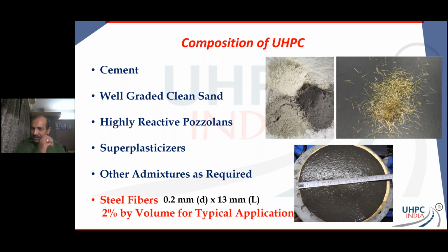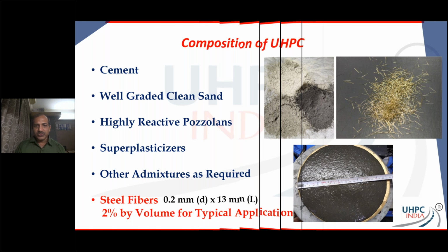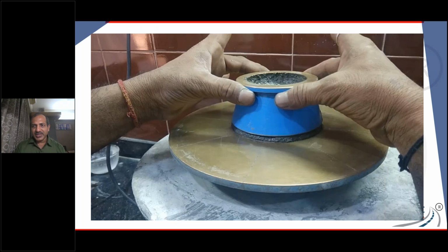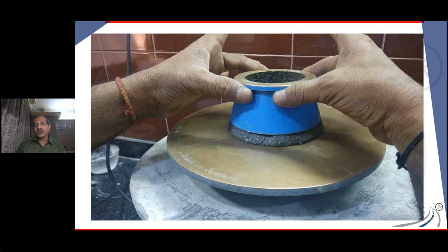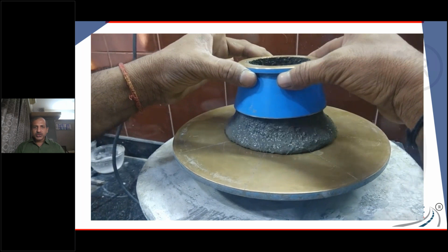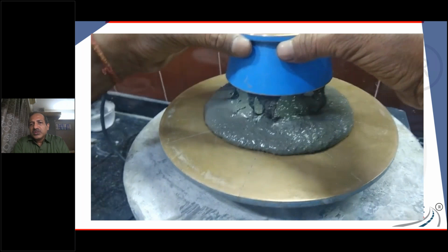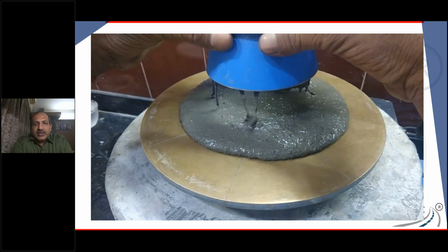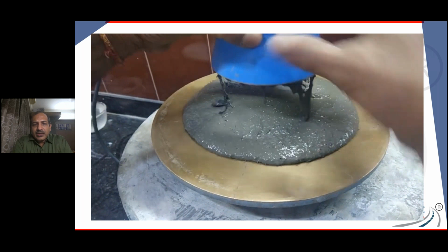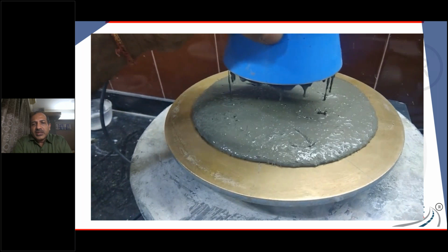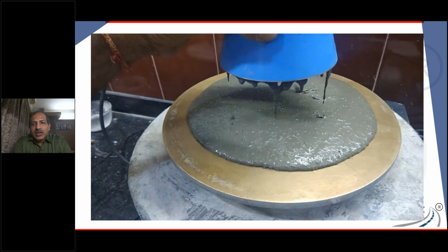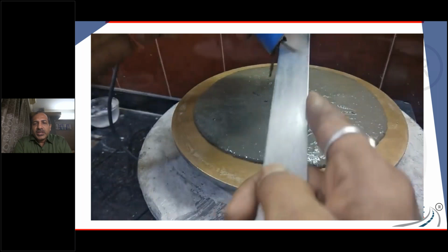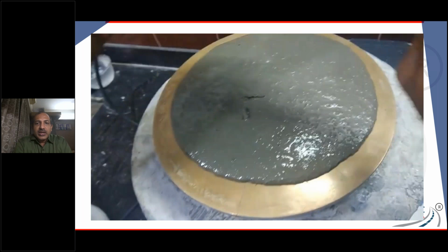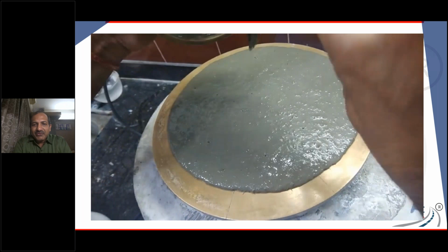And in the pic down below, you can see that UHPC flows very nicely. And I think there's a video over here that you should be able to see. It's a flow test for UHPC, so you're not going to be using anything big. It's a small flow cone that can be used. And once you do that, you would want your flows to be between 180 mm to about 250 mm based on the kind of application that you have, right?